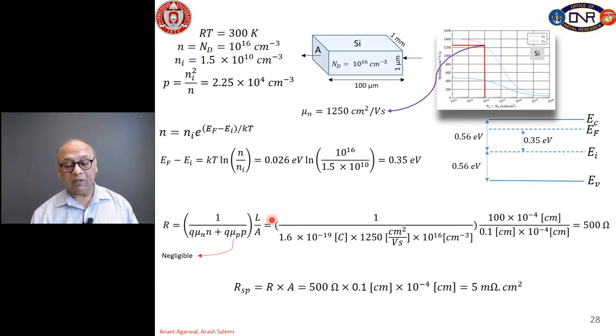And then L is 100 microns, cross-sectional area is 1 millimeter by 1 micron. Watching our units, the charge of the electron is 1.6 times 10 to the minus 19 coulombs. Mobility for electrons is 1250 centimeters square per volt second. Number of electrons is 10 to the 16 per centimeter cube. Length is 100 times 10 to the minus 4 centimeters, so 1 micron is equal to 10 to the minus 4 centimeters. And the cross-sectional area is 1 millimeter, which is 0.1 centimeters, times 1 micron, which is 10 to the minus 4 centimeters. You calculate all this, you get 500 ohms.